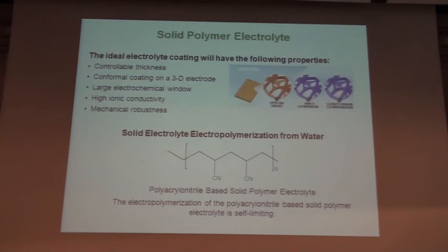Okay, so for the polymer, I'll just go very quickly. This was the biggest challenge. This took the longest amount of time in terms of the development. The polymer electrolyte has to have controllable thickness. It has to conformally coat a 3D electrode. The challenge here is that it has to be stable over a very large voltage range, so it has to be electrically insulating, but it has to be ionically conductive, and it has to be mechanically robust. This is not the polymer that we use. This is just a sort of a cartoon of one of our beginning pieces.